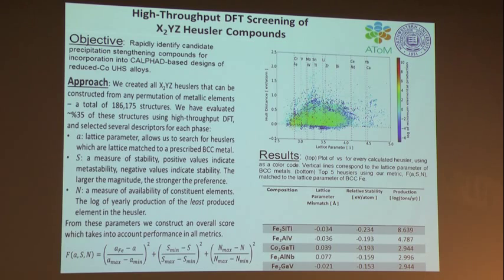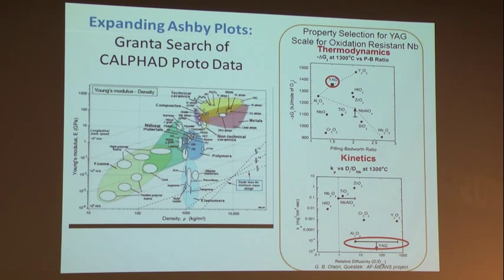phases we're already using. This is an example of that expanded search capability, where currently the Ashby materials selection system is to use these cross plots of materials properties to select them. Here's an early example we did in the design of an oxidation-resistant niobium alloy, where in a similar vein, we're looking here at cross plots of thermochemical and thermophysical properties of potential oxide scales, and then kinetic properties of parabolic rate constants and relative diffusivities in the substrate, so that we were actually able to identify yttrium aluminum garnet as a multi-component scale that could give us an oxidation-resistant niobium alloy, and we're able to actually implement that and demonstrate it. So this is the type of thing that we want to do more of.